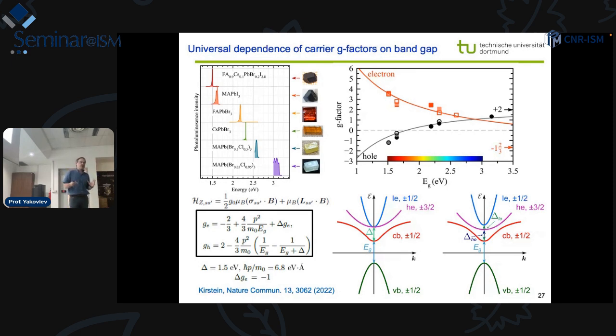And then our main question is whether we can have for this material class some systematics. Systematics in a way that the g-factors depend on the band gap. If we plot the g-factor as a function of the band gap, the anisotropy is shown here by symbols of different sizes, but one can see that it can be very systematic. For the electrons, the g-factor goes down with increasing band gap. And for the holes, it starts from a negative value, crosses 0, and then grows up. The solid lines here are tight binding calculations done with Mikhail Glazov, and they were also improved by k·p theory with these parameters.